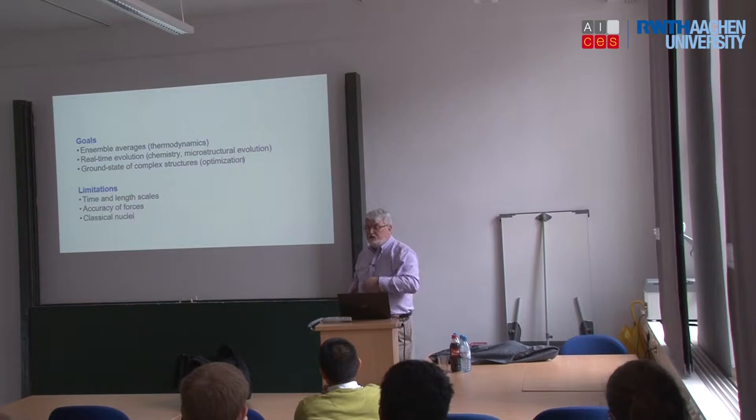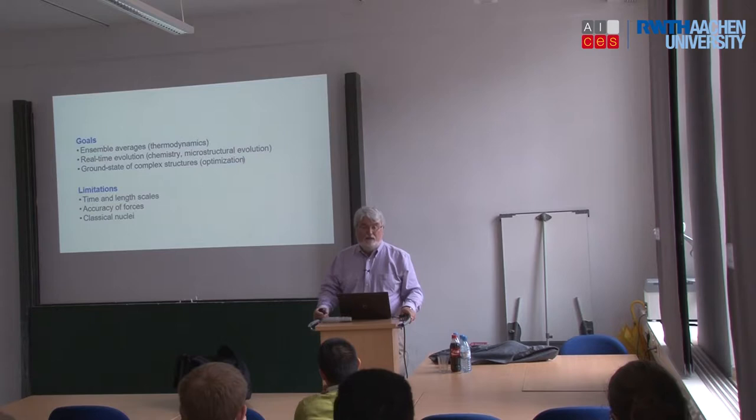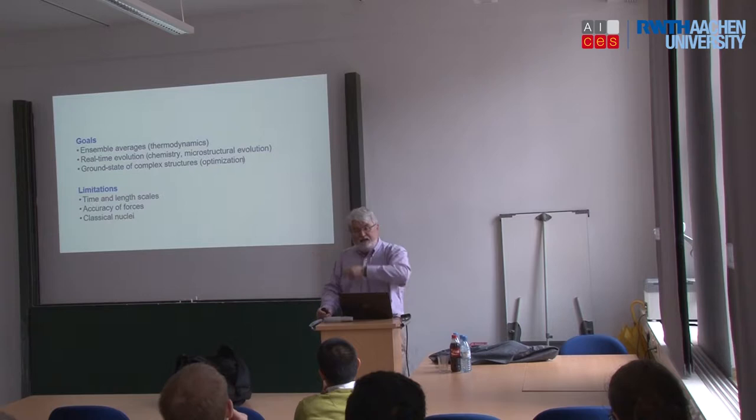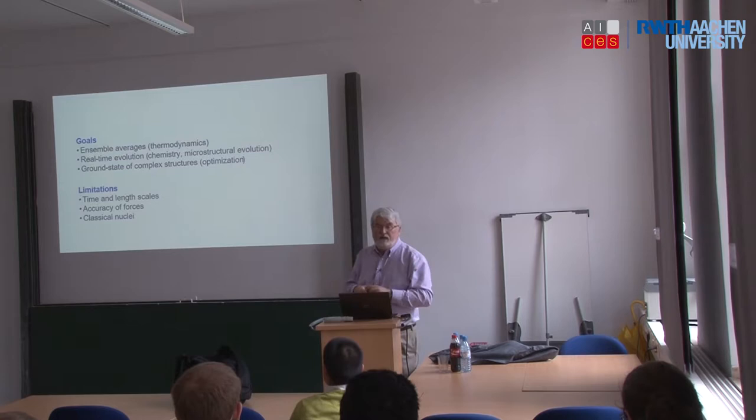As you probably know, DFT methods are restricted to a few hundred atoms, maybe 1,000 at most. Whereas here we're talking maybe a billion at most. But if you're going from 1,000 to 1 billion, that's a factor of 1 million in size. You're going to have to pay for it somehow. And what you pay for is you pay with a less sophisticated description of how the atoms interact with each other. That's the cost.